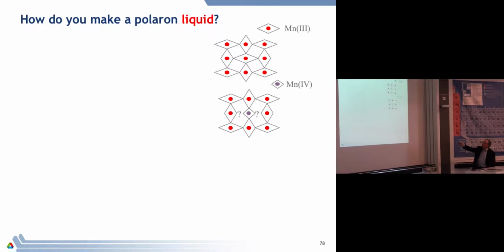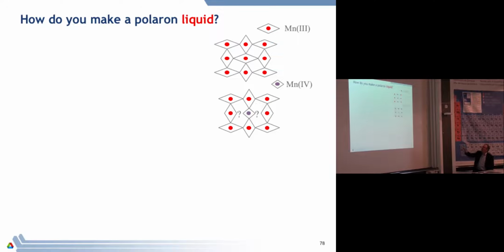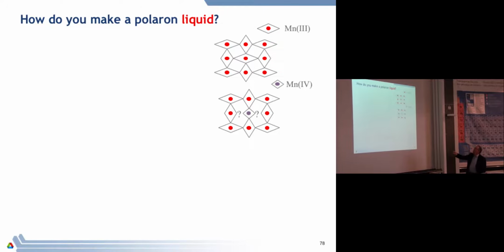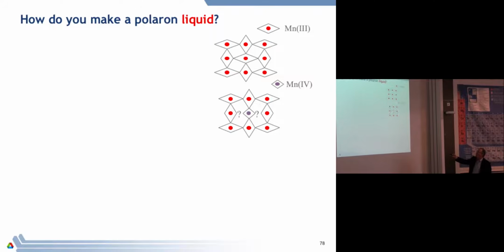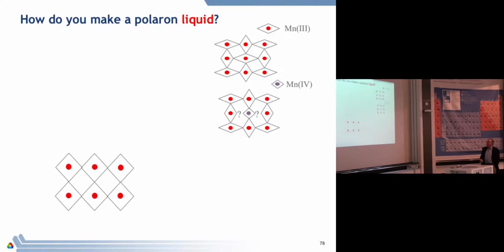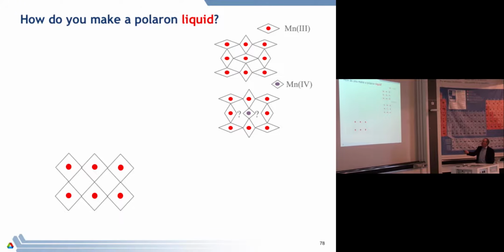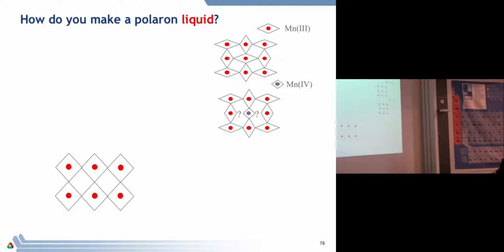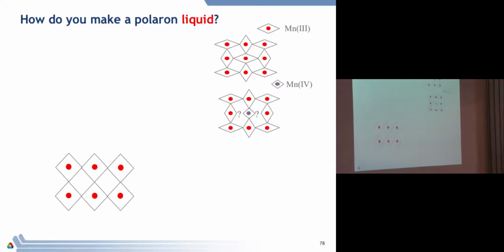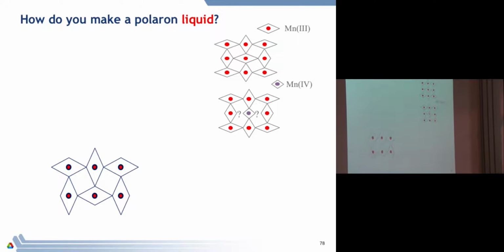If you think about the structure of manganites, the basic motif, if it's deformed, has these squares turned into rhombuses. And if I want to dope it with something and make a 4+ ion, I have to find a way of fitting in something which likes to be small and square in here, and the problem is that is connected to that. Now, that isn't easy to do and have this thing move around, because everything couples to everything else. So for example, if I change the shape of just one of them, it's going to move through the solid and move it around. Is there a way of getting around that?